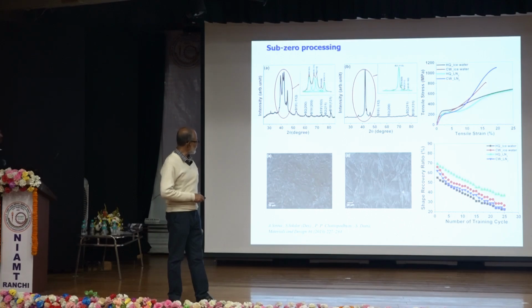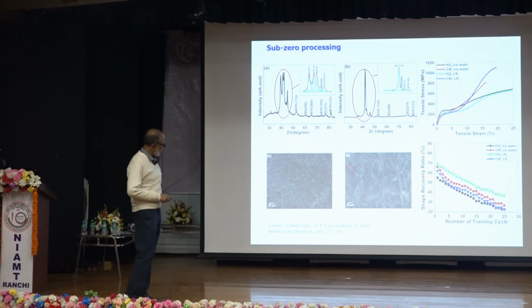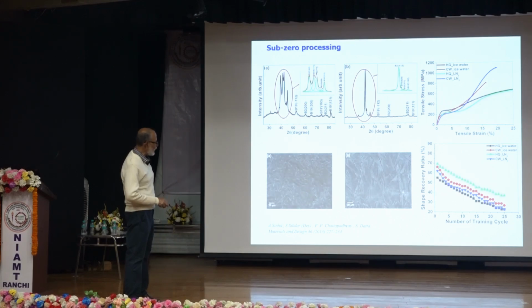Right? And we have a very surprising morphology of martensite. In other cases it was coarse and random, but here the plates are very fine and oriented in one particular direction. That favored the reorientation, coalescence and detwinning of martensite, and as a result favored the shape recovery behavior. From the nanoindentation experiment we also found significant improvement of shape recovery ratio in comparison to others.